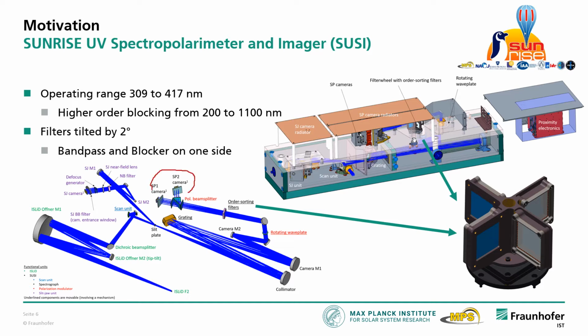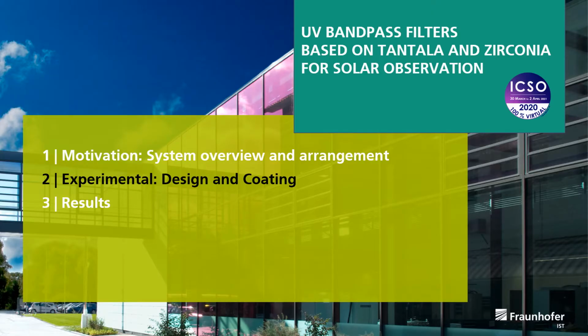with its high-resolution cameras. The filters are used as order sorting filters at this position, and also you can see it here, and they are tilted by 2 degrees. This makes it essential that the bandpass and the blocker are on one side to have no backside reflections and to reduce the ghosts. Experimental part.